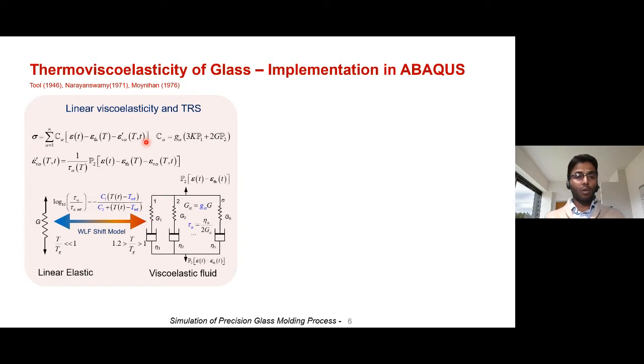There is the energy stored in the springs. In order to compute these elastic strains, you need to subtract the thermal strain and the viscous strain from the total strain. For the viscous strain, I'm assuming that the fluidic behavior follows a Newtonian fluid, and you have a stress versus strain rate relation for it.